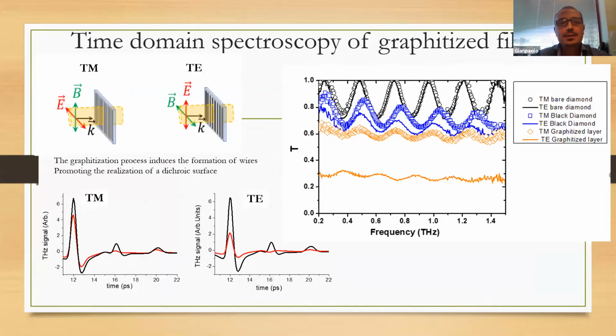And here we have the main results on this graphitized layer. We have performed two different measurements: one when the electric field is parallel to these ripples, and the other one when it's perpendicular. Usually they are called TM and TE polarization. And what we can see is very nice.